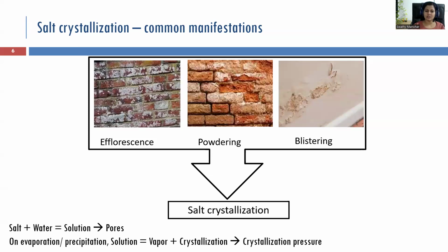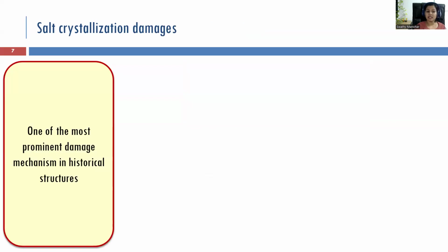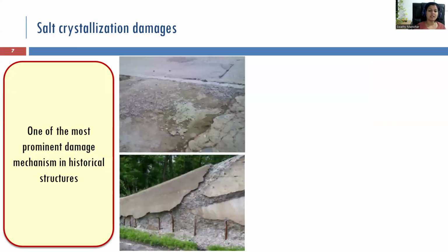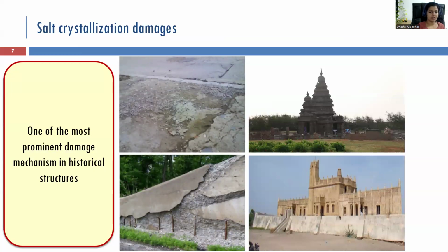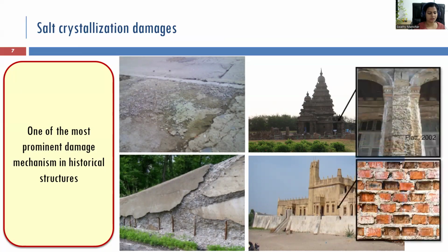If the evaporation rate is much higher, vapor could escape easily directly from the pores and the salt will precipitate inside the pores. This is more damaging because now the crystals can create something called crystallization pressure on the pore walls, which could damage your material. This is called crystallization, identified as one of the most prominent damage mechanisms in historical structures. Not only in stone or brick structures, but even in concrete structures this is prominent. You see examples of concrete, stone, as well as brick structures which are susceptible to salt crystallization damage here, and the extent of damage it can go to.